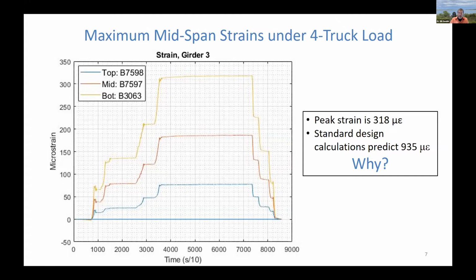The strains vary linearly over the section, as we'd expect. But this also tells us that the neutral axis is really up in the concrete deck. And that's important because that means we've got full composite action out there in this bridge, as we would expect to see. Now, that peak strain of 318 microstrains, though, our standard design calculations with usual AASHTO live load factors, ignoring non-structural elements, predicted about 935, almost 3 times as much strain as we observed in the field.